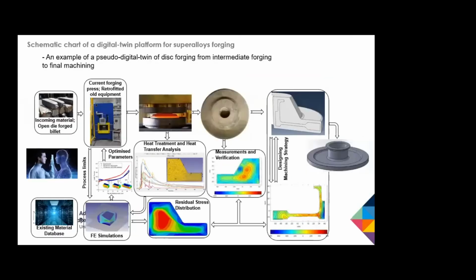Just to give you an example, we actually have got this going pretty early in some areas. This is probably our best example of this. That's residual stress. About 10 years ago, we started experimentally looking at residual stress at the industrial scale, and we've become really good at it. So we've got a broad range of experimental capabilities to measure residual stress with a high degree of confidence from the nanoscale all the way up to a metre or so in scale. But over those 10 years, we've also developed a significant capability of predicting those residual stresses, both under standard quenching systems, but also in directed types of quenching where we're locally cooling at different rates.